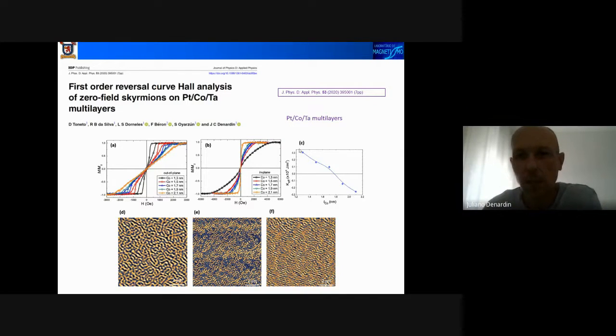And in C, you can see the effective anisotropy of the samples, that is measured basically by measuring the field that is necessary to saturate the sample out of plane or in plane, depending on the easy axis of the sample. I forgot to put the equation here, but it's simple.